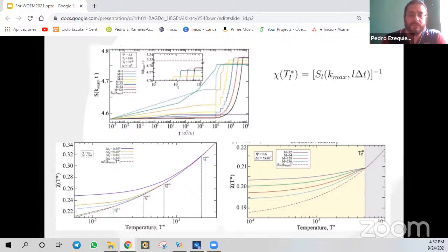In the first picture, you can see the relaxation of the maximum of the time-dependent structure factor for different cooling processes. The inset shows a summary of the final states, and we can see that there is a different final state for different processes. The dotted line is the expected equilibrium state. And we can see that the system never finds the equilibrium state.